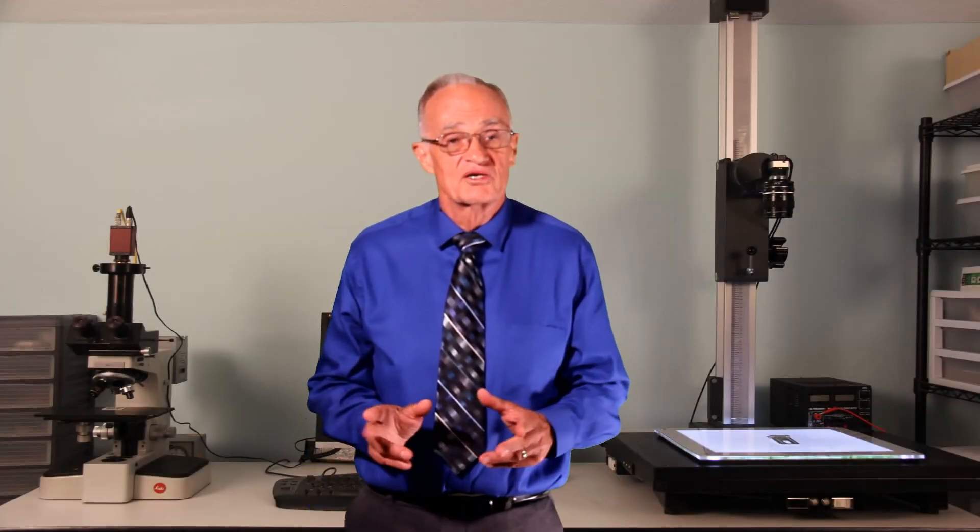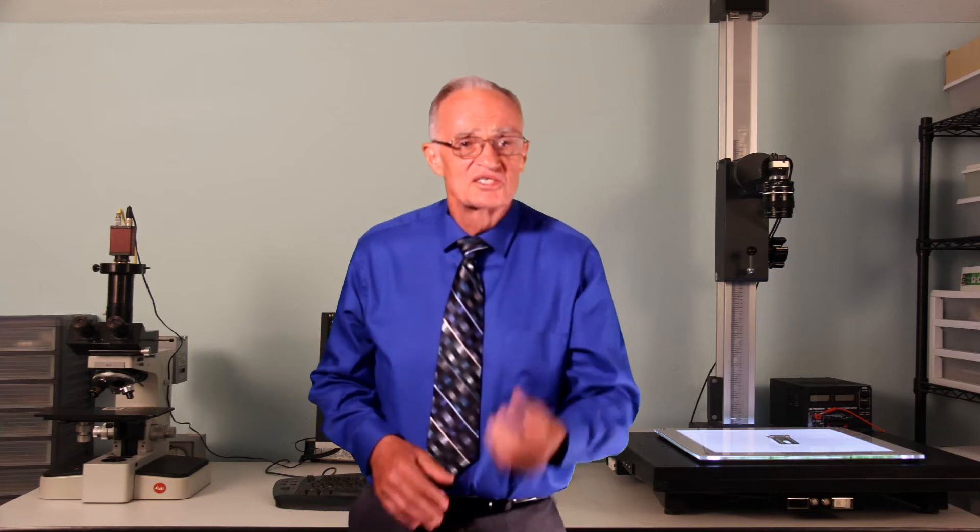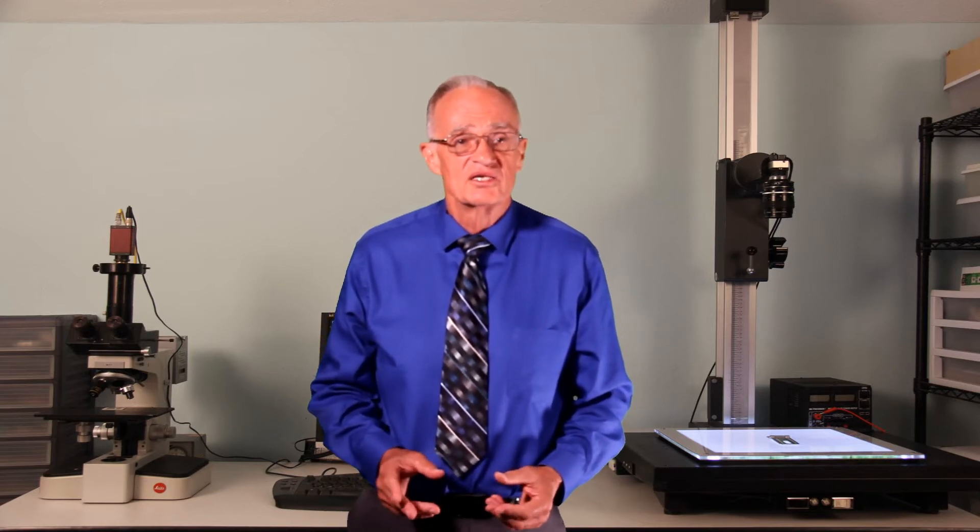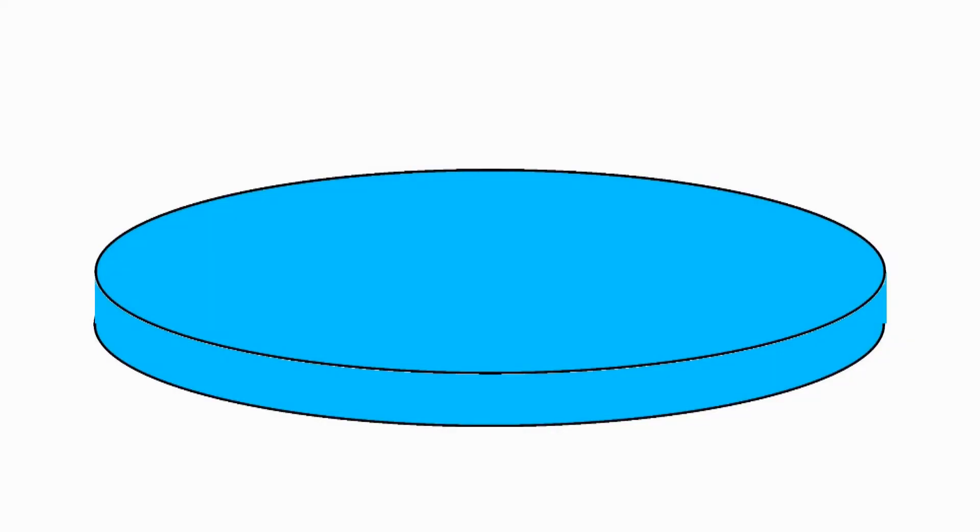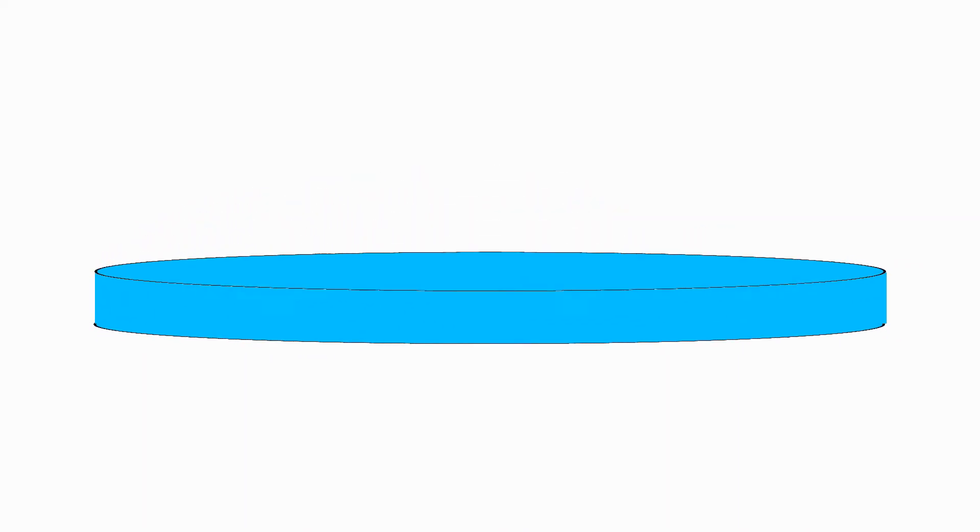Before leaving semiconductor physics, let's look at the very basic steps in fabricating a semiconductor device. The process begins with a wafer of silicon that is heavily doped. The next step is to grow a more lightly doped layer on top of the wafer. This top layer is where the actual semiconductor devices will be fabricated. Into this layer, other impurities are introduced to change n-type material to p-type or p-type material to n-type to build the desired regions, either side by side or one on top of another.